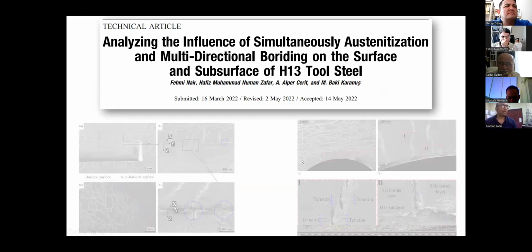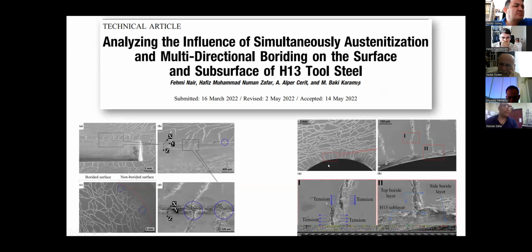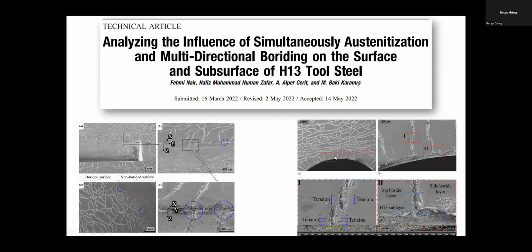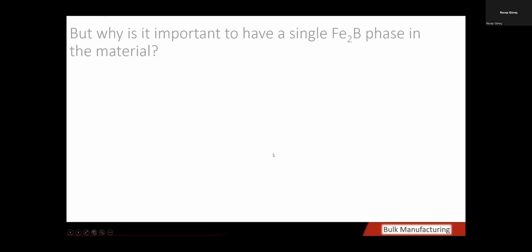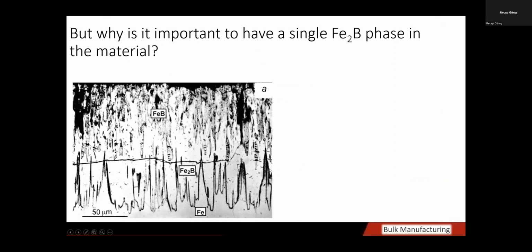Well, that has to do with the cracks which are formed on the borided surfaces. This paper was published 2 months ago, in which we characterized the types of cracks formed on the borided surfaces. This is not related to our study, so I will skip that. But while investigating the cracks, we came to realize that the FeB and Fe2B phases are not compatible, simply because they have different thermal expansion coefficients, and when they are cooled in an unwanted way, they are going to crack at the boundaries.